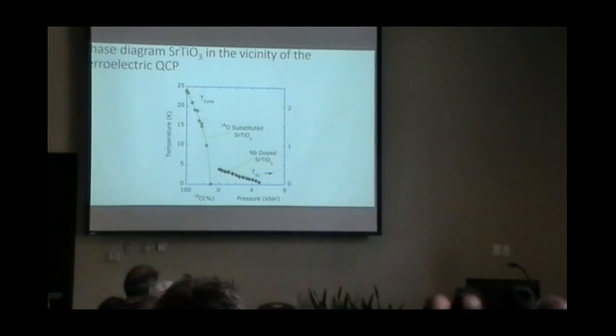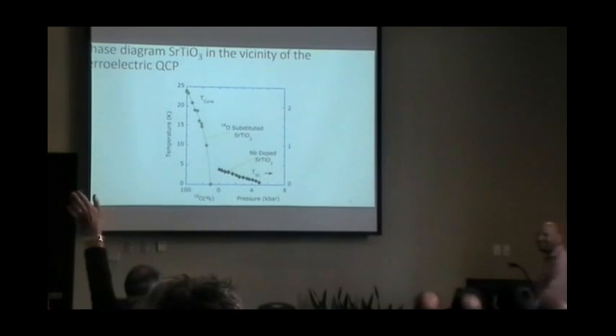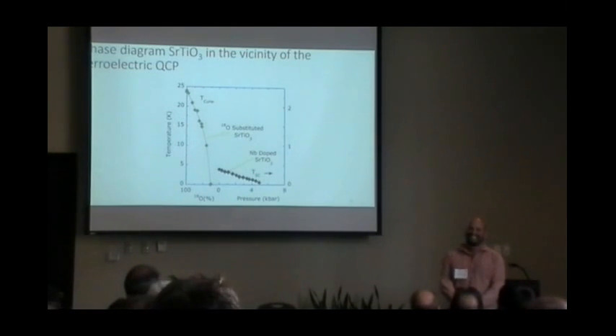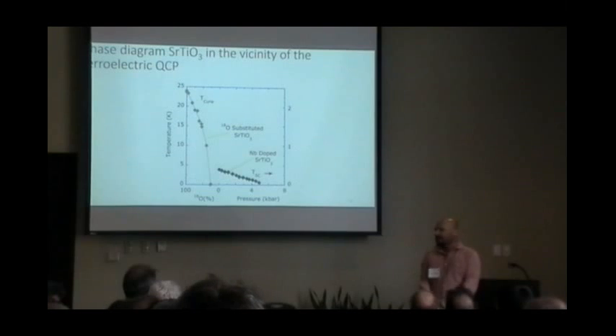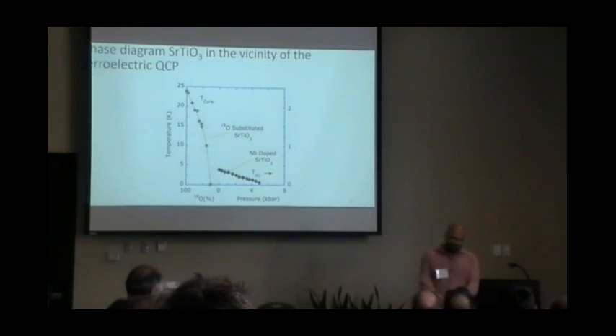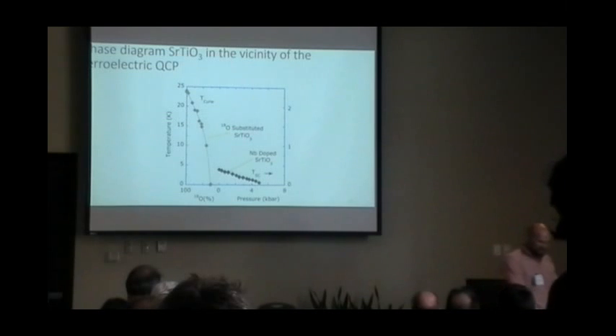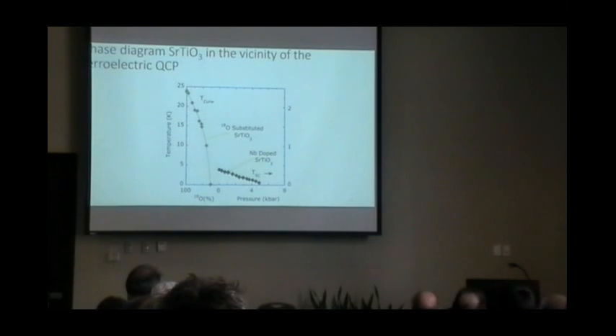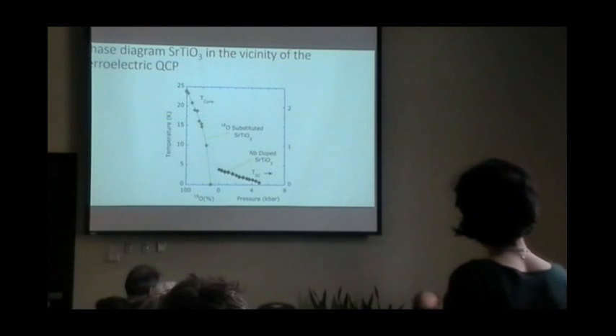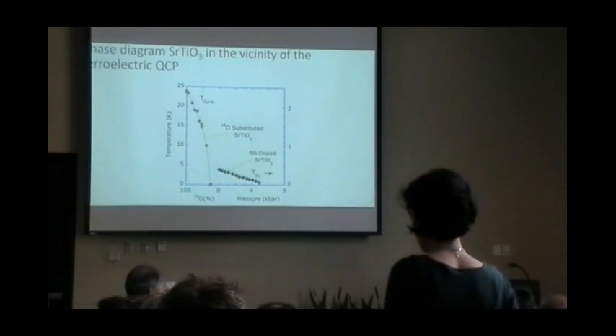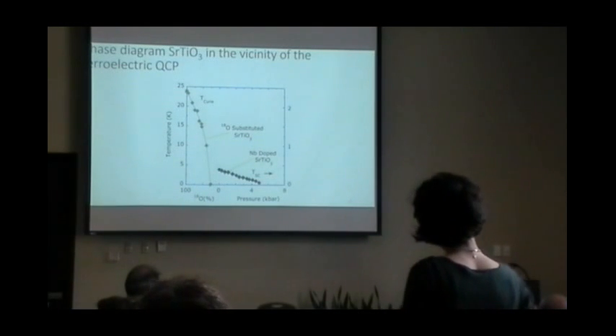I'd be interested in seeing the experimental results on the phonon dispersion after pressure or under pressure. Have you done that, or can you tell me something? No, we have not measured. We have not done any measurement of the phonons under pressure. We have done only these measurements until now for the resistivity data.